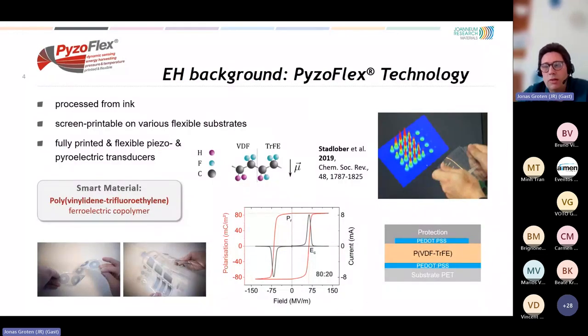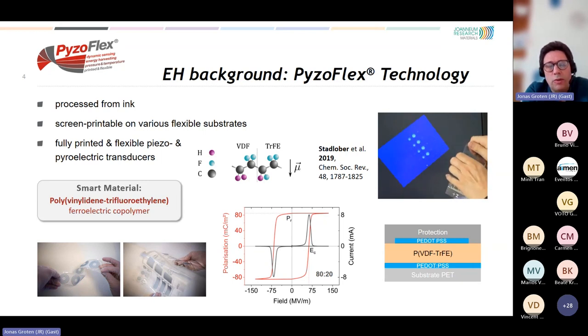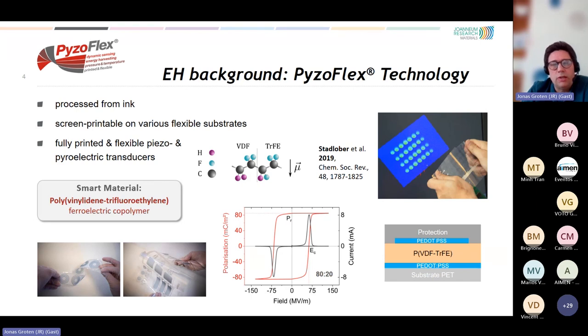So, of course, the material PVDF TrFE is well known in this community. We are using the copolymer PVDF with TrFE because we want to apply it by printing from solution processing. And a good thing is that with the copolymer TrFE, it directly crystallizes in the piezoelectric beta phase. As you are in this research field, we have a long experience with this material and the screen printing of this material, also used for sensing in the so-called PyzoFlex technology. The typical d33 coefficient we achieve is around 24 picocoulomb per Newton in the standard setup. You can find a lot of papers on this material, also from ourselves, from my group leader Stadtlober. There is a recent review where you can look up a lot of properties.